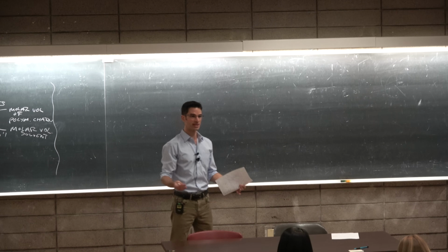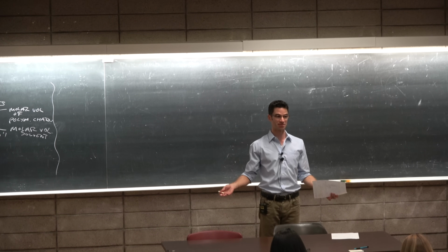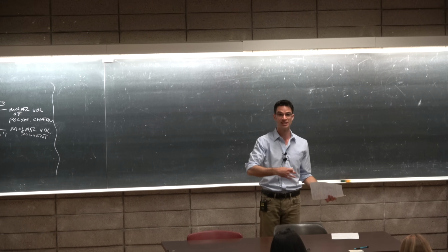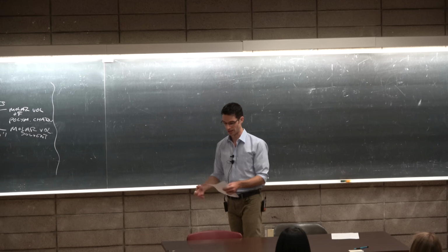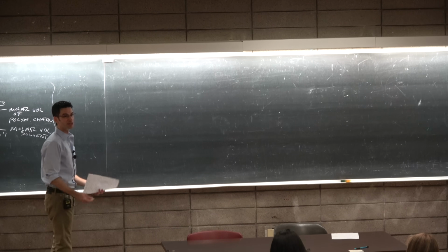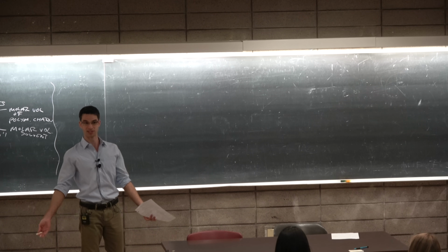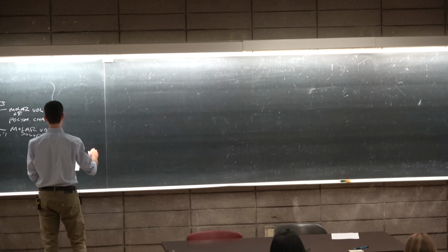So in the end, we're going to get an expression for the entropy of mixing that basically just swaps out the mole fractions from the ideal solution with the volume fractions in Flory Huggins theory. So what's the definition of volume fraction? The reason we do this is because we don't necessarily know the moles, but it's easy to measure the volumes, because we just know the volumes of the stuff that we dump into the mix.